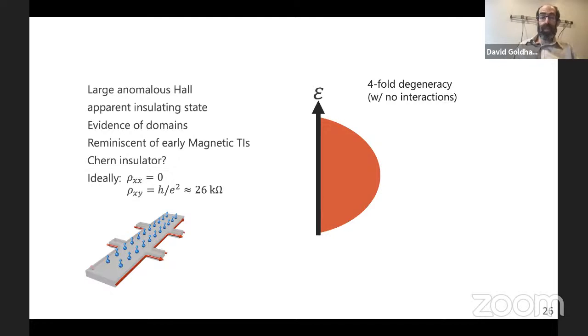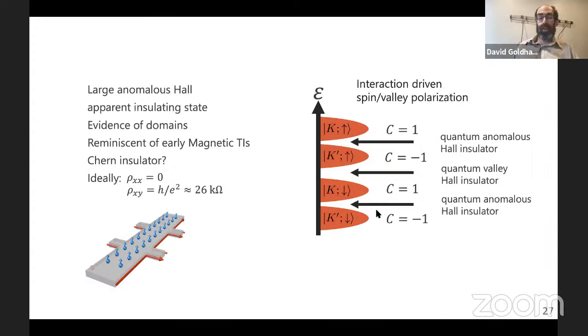But if we allow the system to reorganize and polarize, then you could imagine one simple scenario is that it polarizes in both valley and spin. This fourfold degeneracy or near degeneracy gets broken, and we fill 3 of these valley and spin states and leave one of them empty, in which case we would have a net polarization in both valley and spin, and we would have a net Chern number because of the valley. So that's a simple picture of what might be going on.